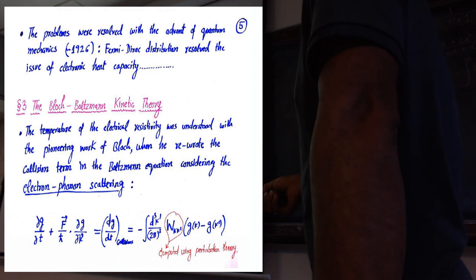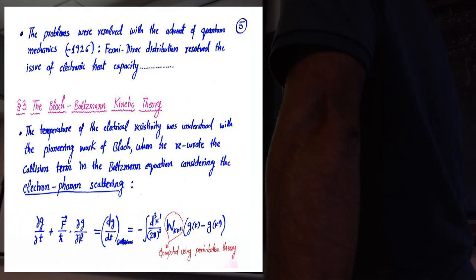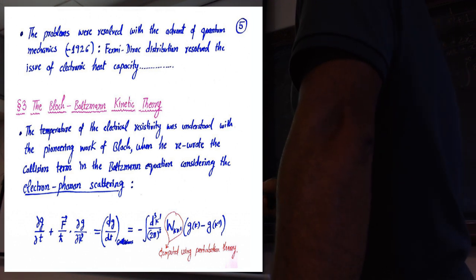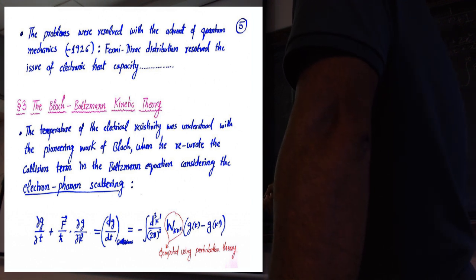So he wrote the Boltzmann equation, which was already there, and applied it to electrons in metals. He wrote the collision integral in such a way that, here is the standard term: del g by del t is the non-equilibrium distribution function, and this is the drift term, del g by del k dot F, where F can be charge times the electric field. This is the collision integral. The collision integral has this transition probability, the rate W k k prime, which can be computed from Fermi's golden rule.